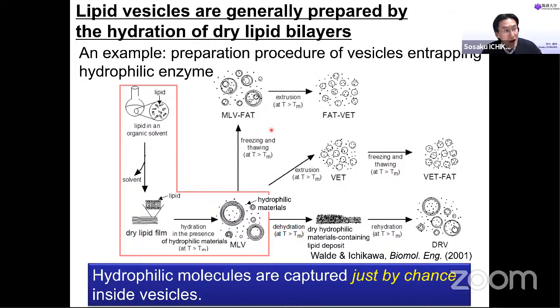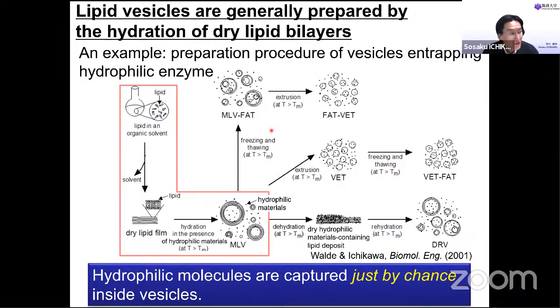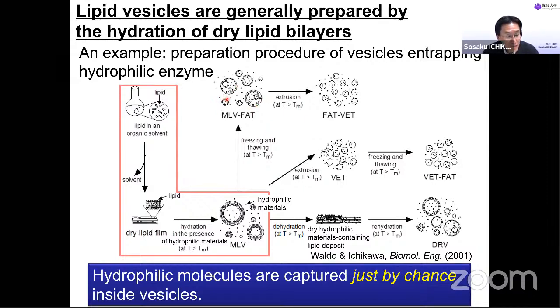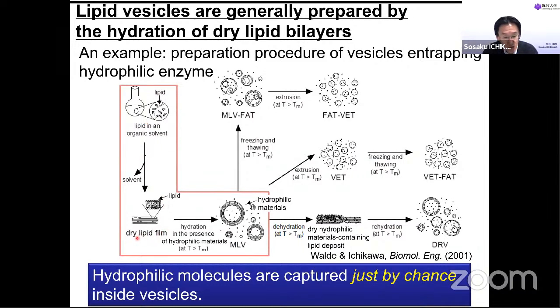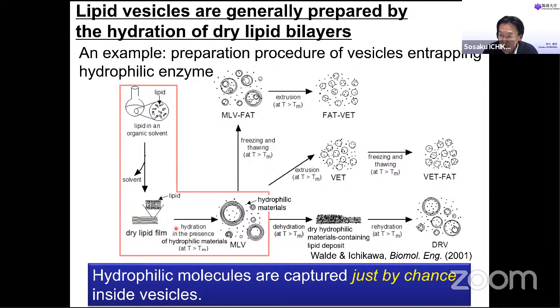So this is the illustration of how to prepare the lipid vesicle. This is a general preparation procedure. Firstly, the bilayer-forming lipid is solubilized in an organic phase like this. In many cases people use methanol or chloroform. After that, evaporate the solvent. We get the dry lipid film at the bottom of the flask. Then this dry lipid film can be hydrated by adding water, then vigorous shaking. This dry lipid film spontaneously makes the lipid vesicle.